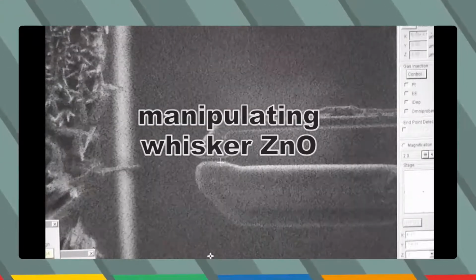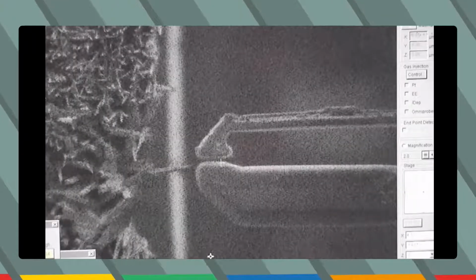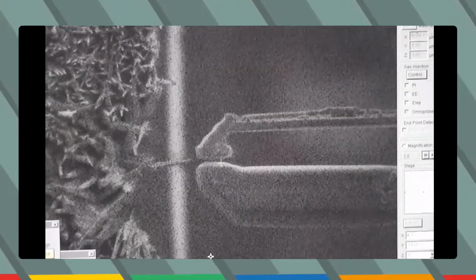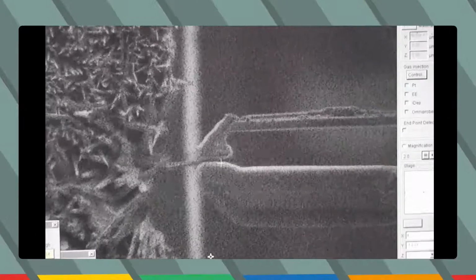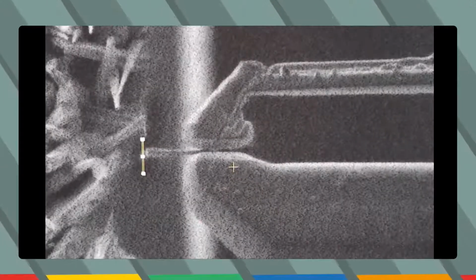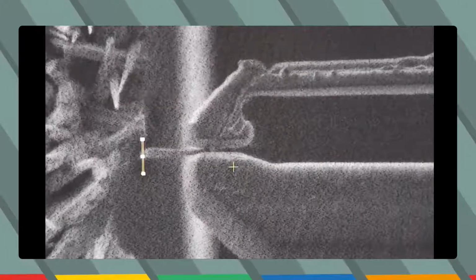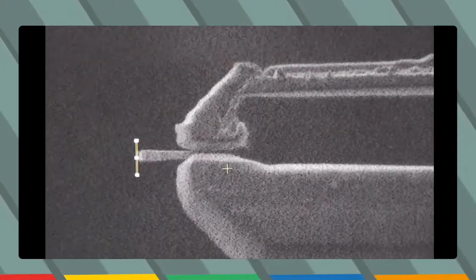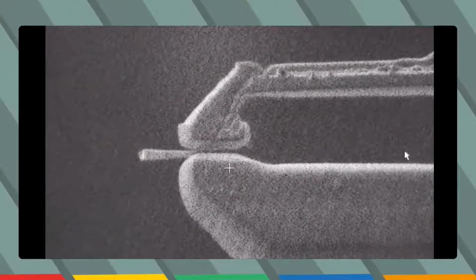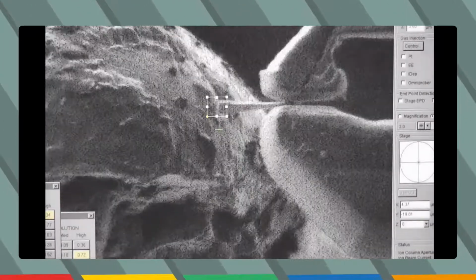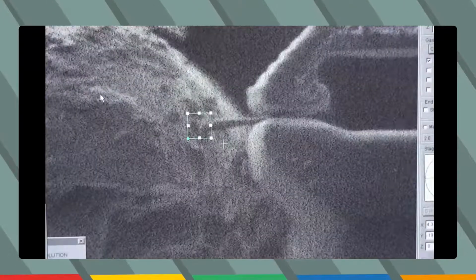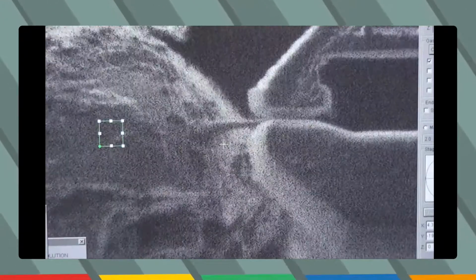We use zinc oxide for manipulation because this material has fibrous structure. The width of a single whisker is about hundreds of nanometers and we cannot see it by eye. Using nanotweezers, we cut off one whisker and fix it on a copper grid. This grid is 3 millimeters in size and we move it to an electron microscope for atomic level analysis.